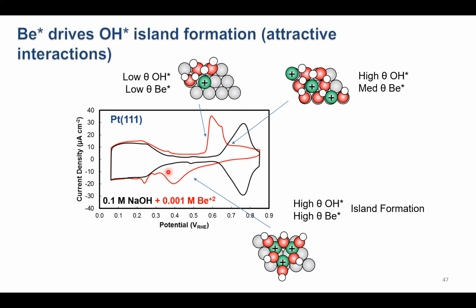And so effectively what we're seeing here is what we would call a first order phase transition, which is not commonly seen in electrochemistry. We see second order phase transitions. That's the sharp peak that we see in the OH adsorption peak on platinum 111 in acid. And so this is actually a first order phase transition where, again, the beryllium makes the interactions between adsorbed OH so attractive that we form islands of hydroxide on the surface that are more stably adsorbed. And so they don't desorb until we go to much lower potentials.